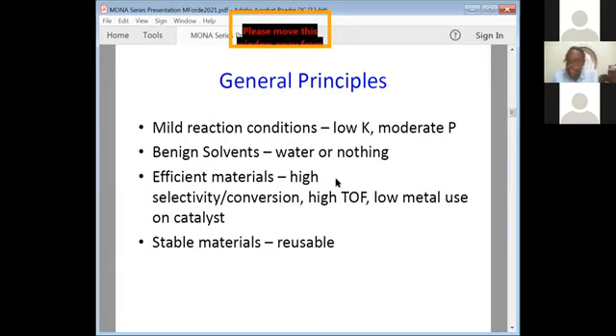The materials must be efficient, so that means high conversion or selectivity, and we prefer selectivity to conversion because selectivity tells us something about the active site that conversion doesn't. Turnover frequency should be high or appreciable. Low metal use, since these are metal nanoparticles that we're using for catalysis, and stable or reusable materials, which we check at the end, right? And we haven't paid enough attention to that, I suppose, but in the future we will.